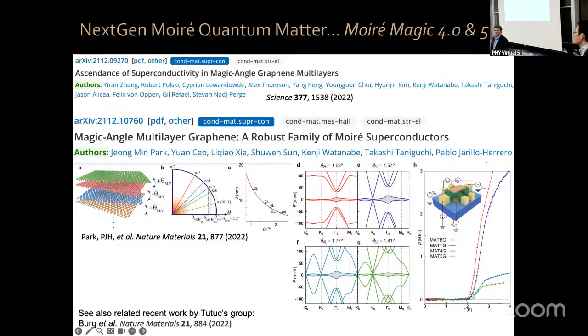Very good. So the short answer is we don't know, but there are things that are already breaking the symmetry naturally. The electronic structure in the simplest model is symmetric, electron-hole symmetric. But actually, when you do more refined models of the electronic structure, it's already not symmetric. So that would give you a natural asymmetry.